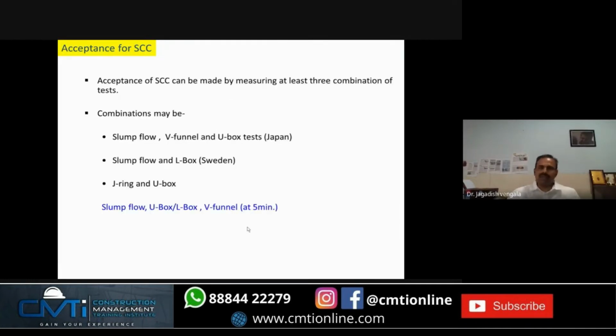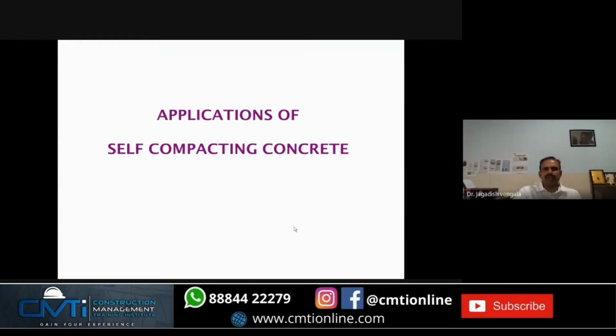And how can you do all the tests? So what is the acceptance for SCC? You can do at least 3 combination of tests. Combinations: Japanese, what they do, slump flow, V-funnel, U-box. Sweden, they do slump flow and L-box. J-ring and U-box, Europeans do. And slump flow, either U-box or L-box, and V-funnel 5 minutes. This we found better, based on our experiments.